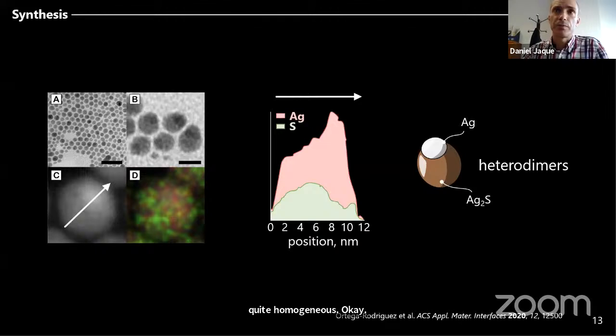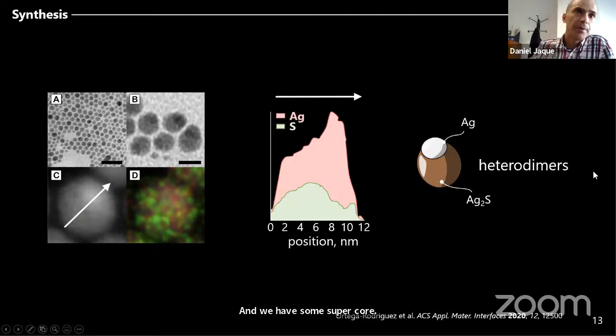Okay, these are the nanoparticles that we have synthesized by this method. You can see that the composition between silver and silver sulfide, between the different elements, is quite homogeneous. Okay, and we have some silver core surrounded by silver sulfide, which we call heterodimers, and this seems to be the best condition to reduce the number of defects and to improve the luminescence of the system. Okay, so then you can get a quite high luminescence intensity.